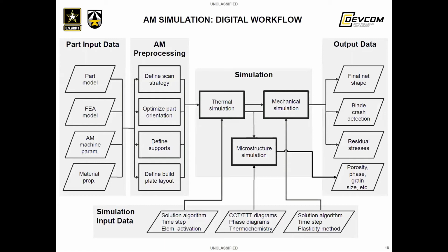And then on the right side, you can see just the types of output information that you get from these simulations. You can simulate the final net shape of the part. You can, again, detect failure events like blade crash events. You calculate residual stresses. And then you can also get microstructural information, as I listed before, porosity, phase content, and the like.